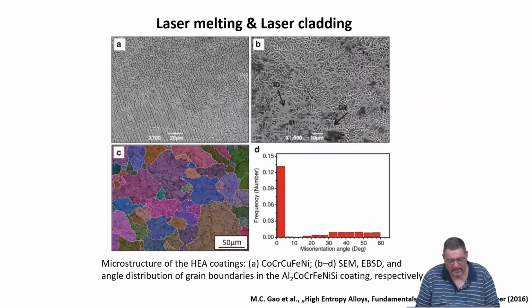And otherwise, it's often that you see dendritic type solidification structures, which again tell you there was a rapid solidification process and there was either constitutional or thermal undercooling, so the solidification front has become unstable, dendrites have formed.